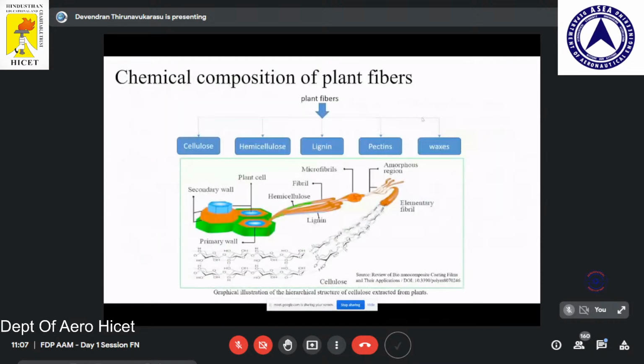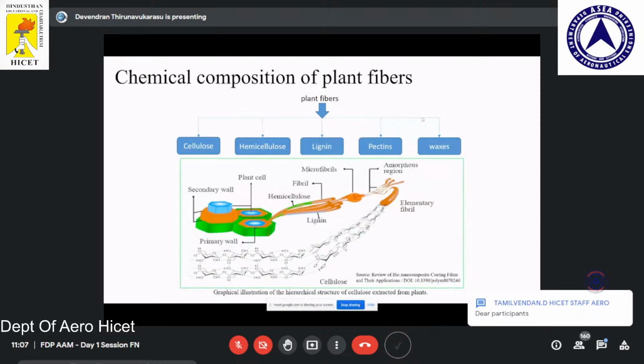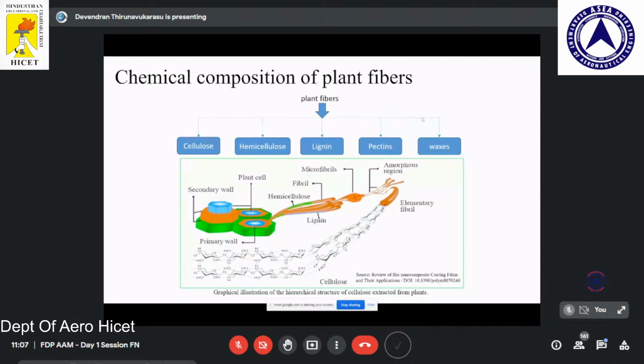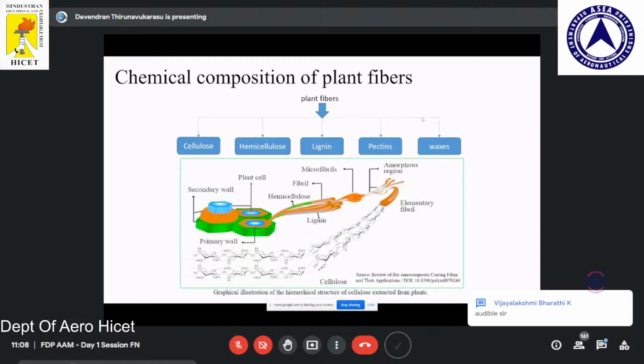And this is the chemical composition of plant fiber. The cellulose is the main ingredient. From this, we have to extract the cellulose and then the nanofibers. So that is the process. The hemicellulose we have to remove with some alkaline treatment, and the fiberization. Next, microfiberization. Next, we have to split it into the elementary fiber. That elementary fiber, we have to process multiple times. We'll get the nanofiber from it.